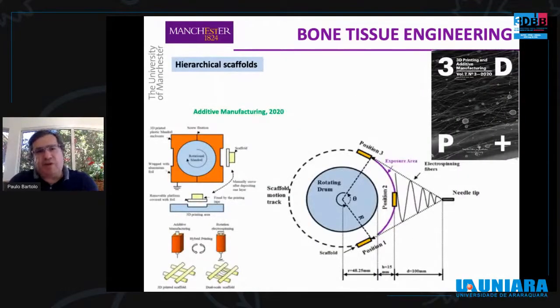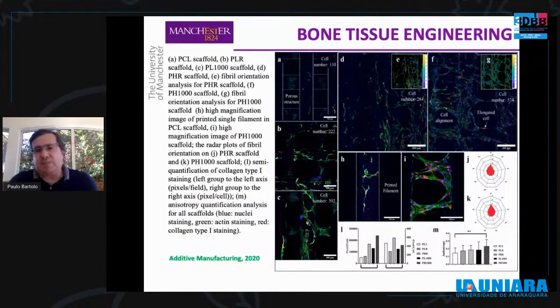We're also designing and producing hierarchical scaffolds through a combination of multiple techniques. Again, this year, we published a paper in 3D Printing and Additive Manufacturing. It was also highlighted on the cover, where we created dual-scale scaffolds using a setup combining extrusion additive manufacturing with non-rotational electrospinning. And more recently, we published another paper in additive manufacturing where we describe a different setup, again using an extrusion-based process, but also a rotational electrospinning system. The results show that by optimizing the processing conditions, it was possible to obtain high mass density with highly aligned fibers embedded in the scaffold.